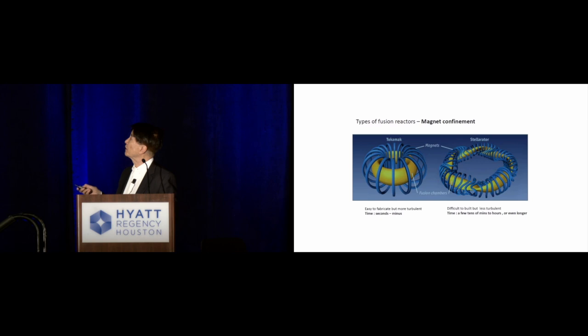But with all these things going on for superconducting materials, one of the important applications is for fusion. In order for fusion to happen, people are talking about magnetic confinement. There's the tokamak machine and the stellarator over there, two types. In order to confine the plasma, you have to use a magnetic field, because you don't want the plasma to get in contact with the walls and so on. Only a magnetic field can do it, and only high-temperature superconducting material can do it, because it has a high transition temperature and, in addition, a strong critical field. And so now people are working on it.